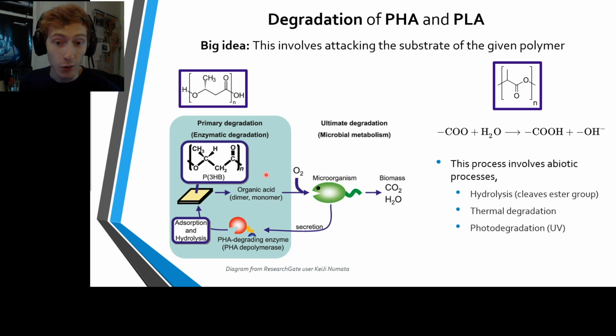Now, here we come to an important point, which is looking at the degradation processes. After all, this is all the efforts of synthesizing efficient plastic being really put to use now. After the plastic has been used and disposed of, the important thing is that the material can be broken down into its constituent molecules. The decomposition process of PLA and PHA plastics are far better than current oil-based solutions. Most notably, PHA plastics surpass PLA in their ability to decompose via microbial enzymes. Just looking at the substrate alone, there's more room in PHA plastics for interactions to occur within the carbon chain, unlike PLA, which is slightly sterically hindered with its placement of the methyl and oxygen groups. As such, in the case of PHAs, microorganisms can easily enter, break down PHA, and use the organic acid as a food source to keep them working hard.